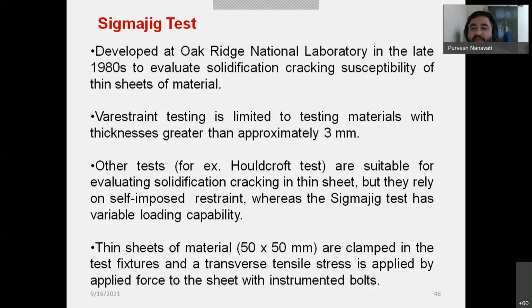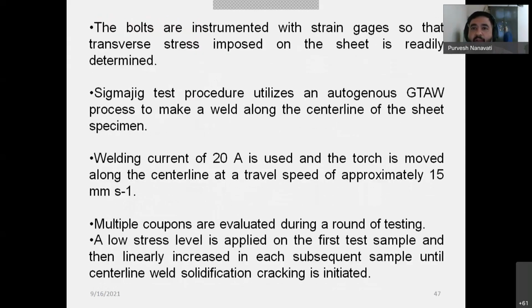So if your thickness is less than 3 mm, you will go for another test. That is the Sigmajig test. So in the Sigmajig test, you can go for thin sheets of materials, like 50 by 50 mm, clamped in fixtures. So note it down: it is an external restraint test, a mechanical restraint test. And the transverse stresses will be applied on the test plate with an instrumented bolt, and bolts are instrumented with strain gauges, so you can measure the amount of strain developing or induced in a test plate.